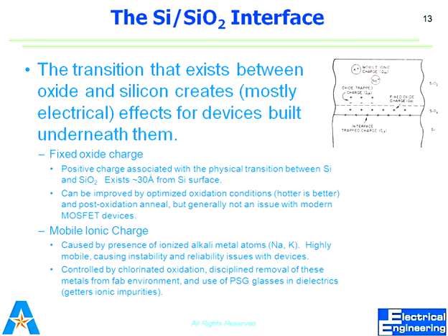And this is named as QF. We call it QF, that is fixed oxide charge. This QF also depends upon the growth condition: in case of wet oxidation, QF is always high, and in case of dry oxidation, QF is always lower, because these are actually the contaminations, or I would say defects. So that's why dry oxidation is always better quality as compared to wet oxidation. These are not very important, but you should at least know about that.